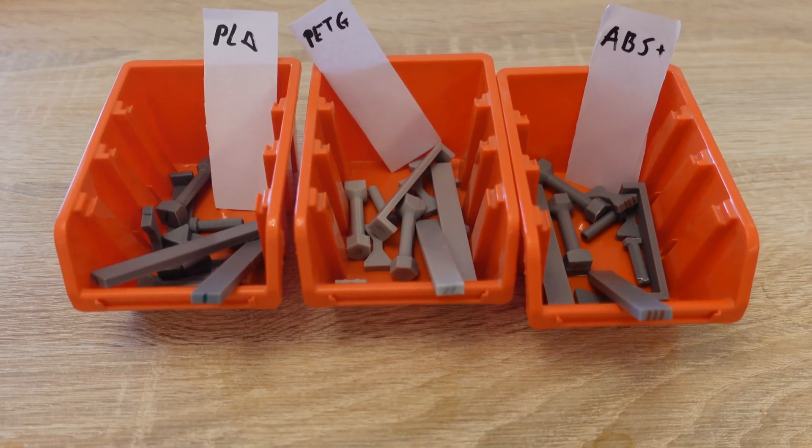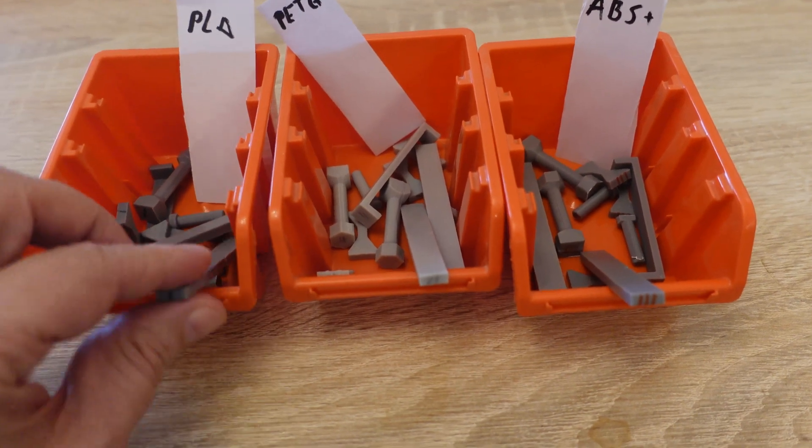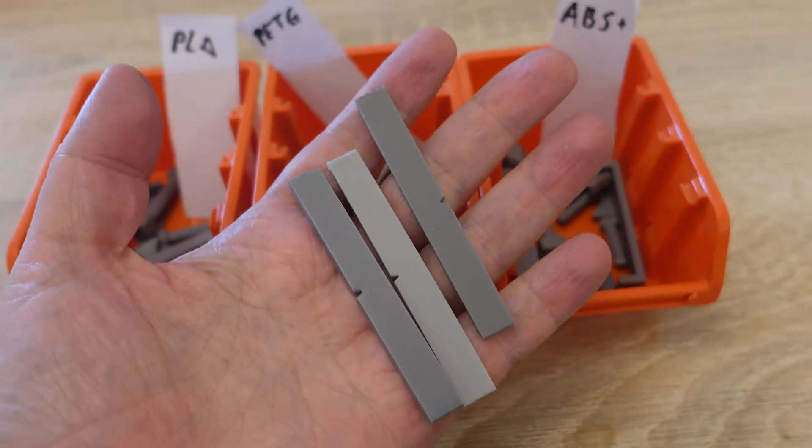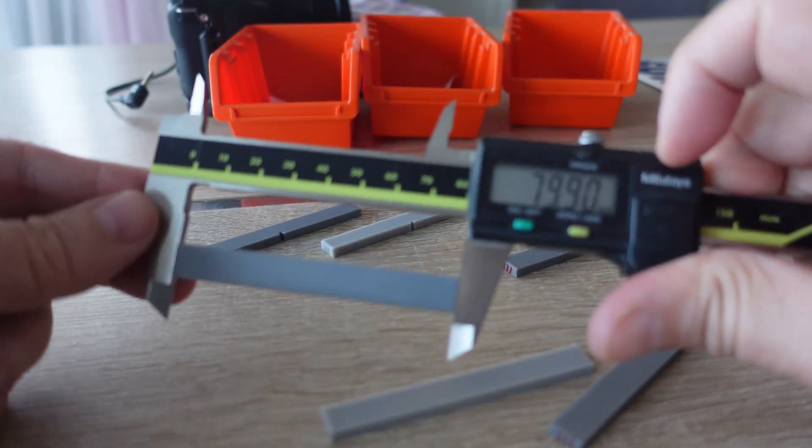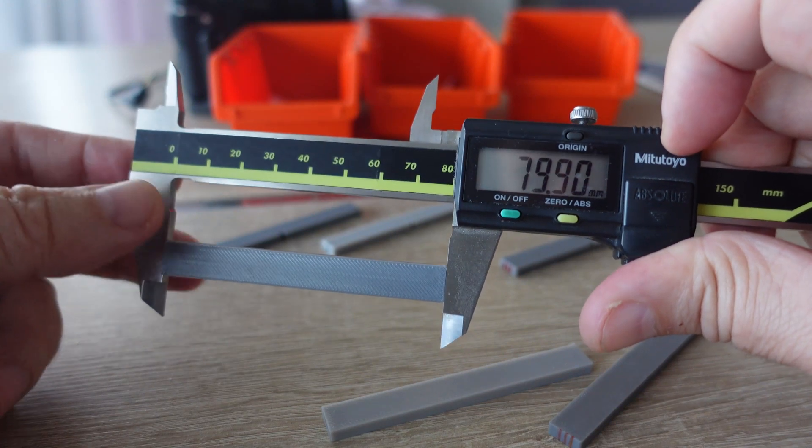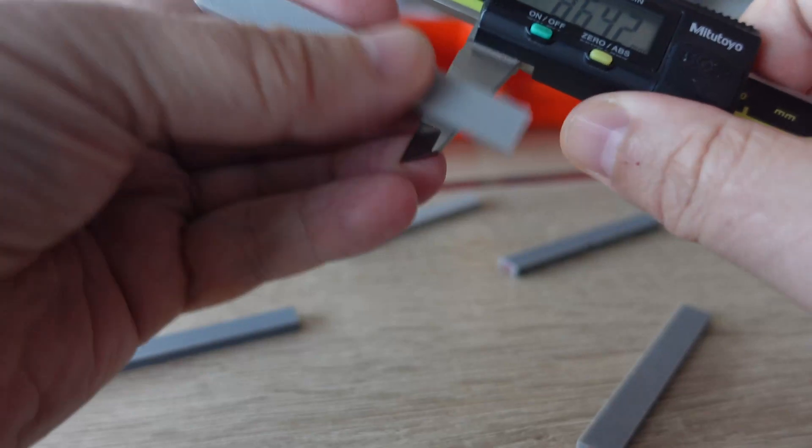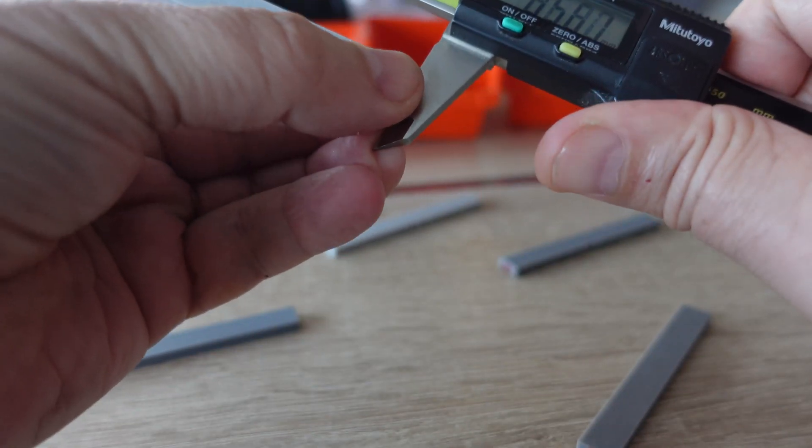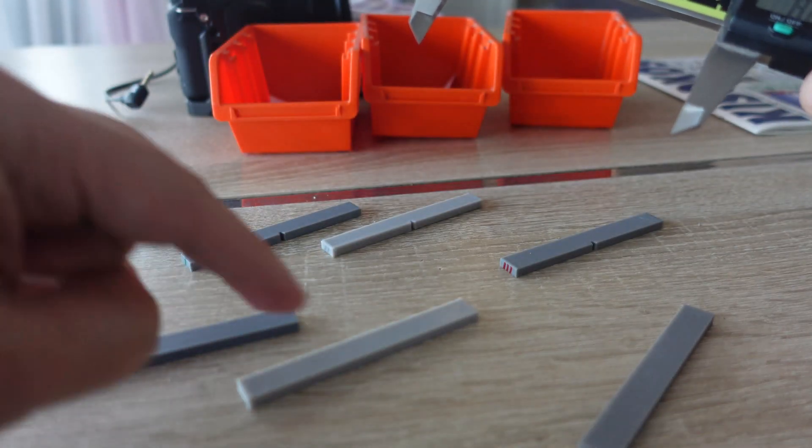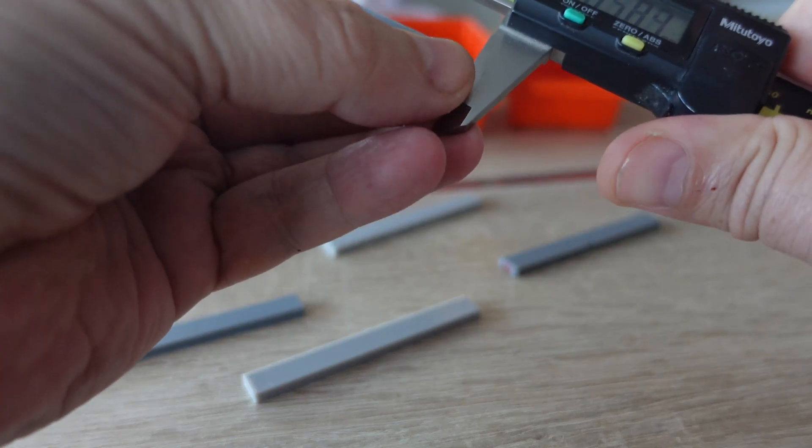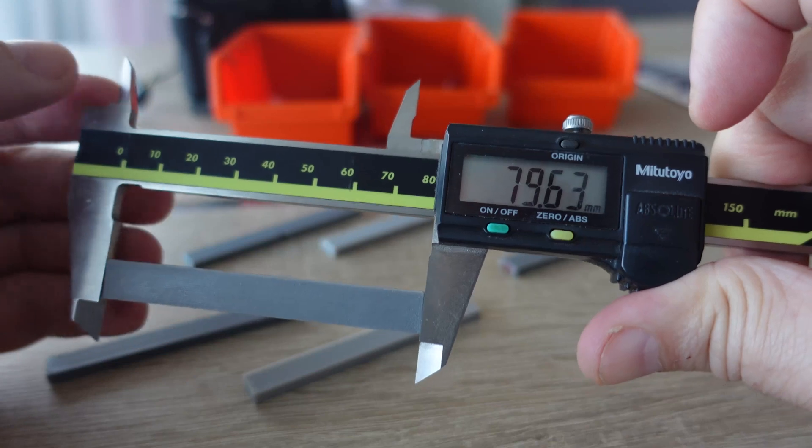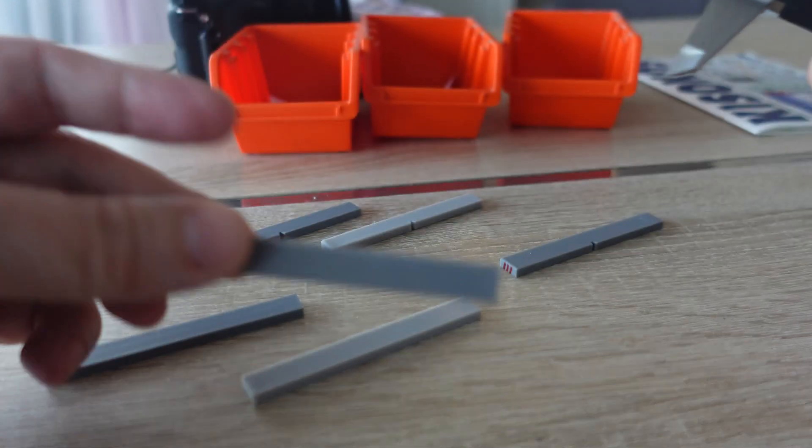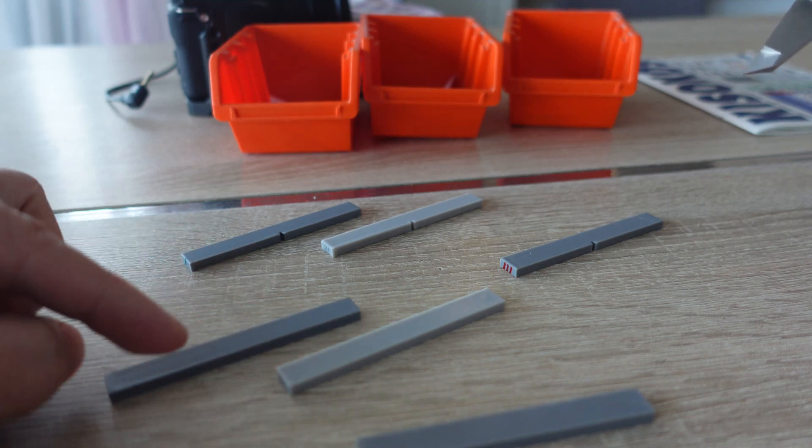They are ready for mechanical testing. I even marked them with these lines, but before that let's talk about shrinking. Interesting situation—this dimension should be 80mm. The PLA is 79.9mm and the PETG is more accurate actually, 79.96mm. Usually with PETG we have a little bit less shrinking compared to PLA. This ABS has typical shrinking of 0.5%, its dimension is 79.63mm. This is typical for ABS, better than average PETG, and worse than average PLA.